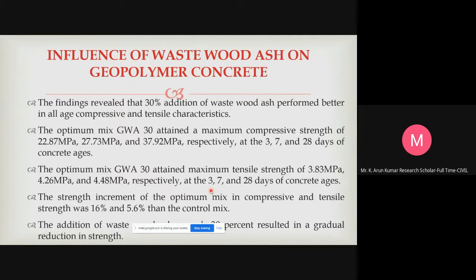Then the optimum mix, 30% mix, has attained a maximum compressive strength of 22.87 MPa at 3 days, 27.73 MPa at 7 days, and 37.92 MPa at 28 days. So we designed for an M30 mix, but by the addition of wood dust, we have achieved 37.92 MPa at 28 days.